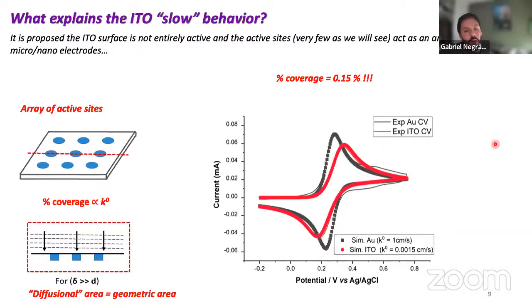But there is a problem with ITO because if you record a voltammogram, so if I have a big piece of ITO, let's imagine I have like a 0.5 millimeter electrode, which in electrochemistry terms is quite big. And I record a cyclic voltammogram there on a very nice reversible species like hexaammineruthenium or ferrocene methanol or whatever you choose to do so. The CV is going to look like this, the red one here, which looks sort of nice, but you can see that there's a little bit inclined. So the peak distance is a little bit larger than we expect. But more than that, the peak current is not what we expect it to be, right? So this is just compared to a gold CV here in black, and they have the same area, same concentrations, same everything. And you can see they look quite different.